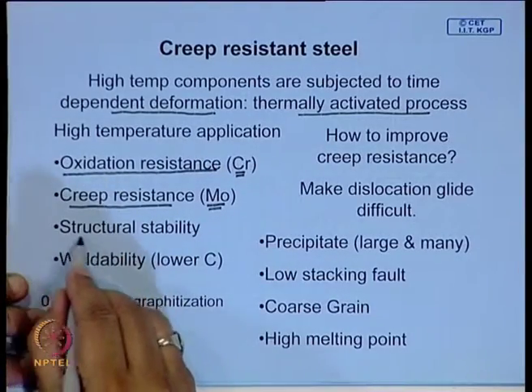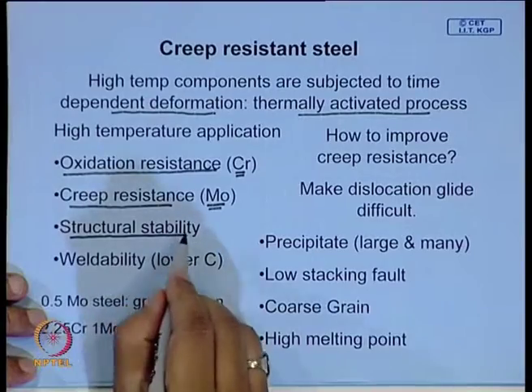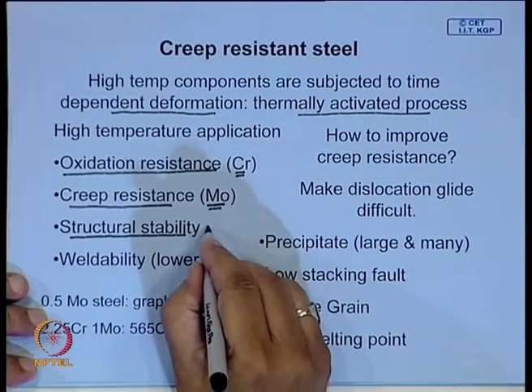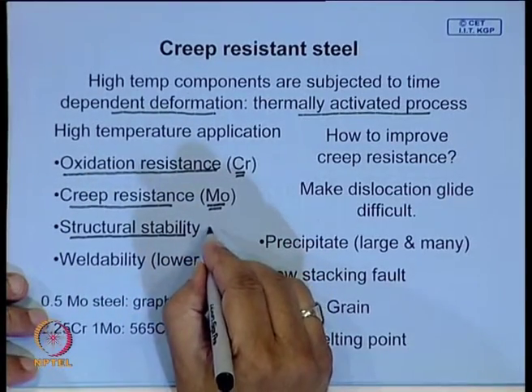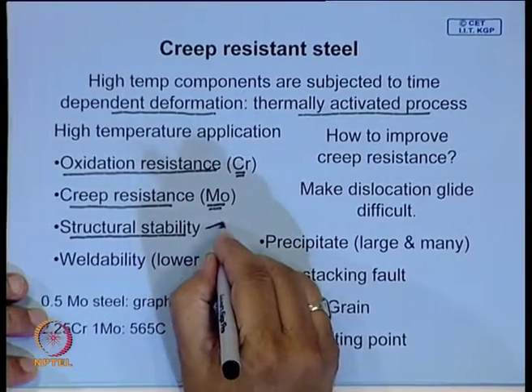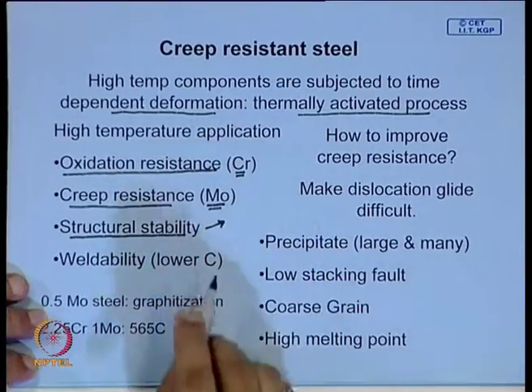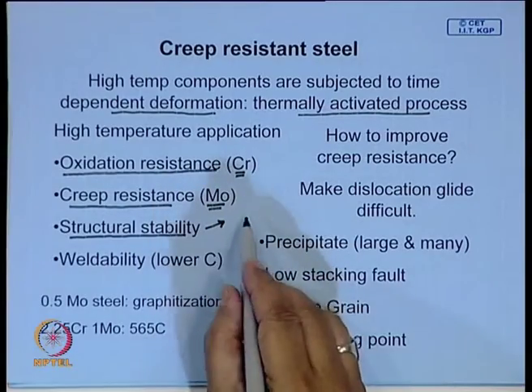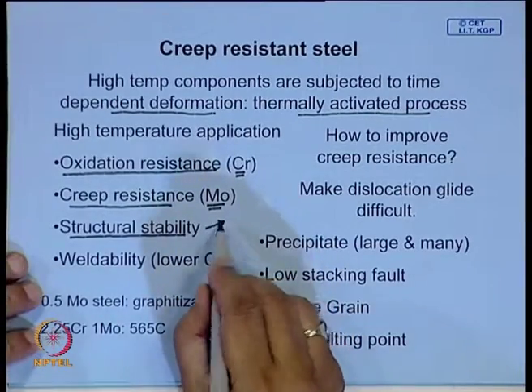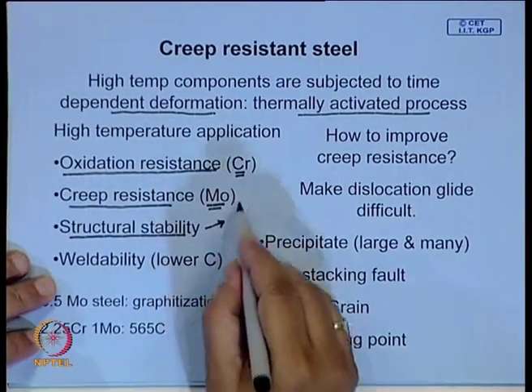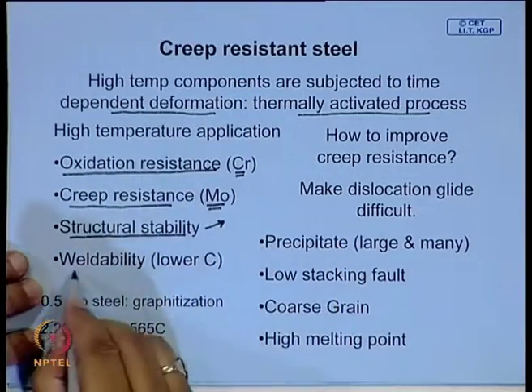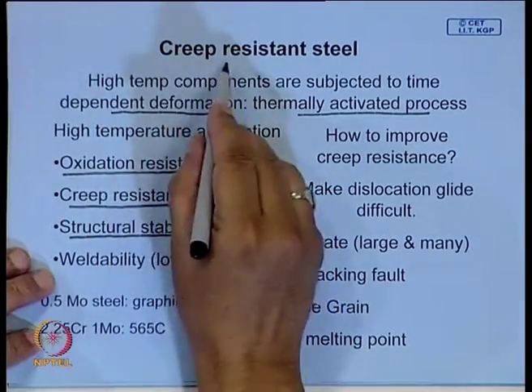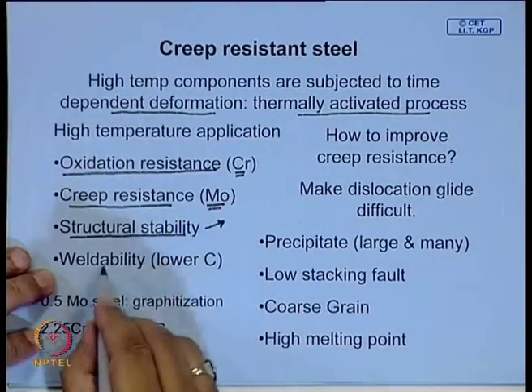Another is structural stability. It should have a very stable structure, and it should preferably have some stable precipitates, and stable precipitates are coherent precipitates. Coherent or semi-coherent precipitates are most stable. So, you look for such features in the alloy.